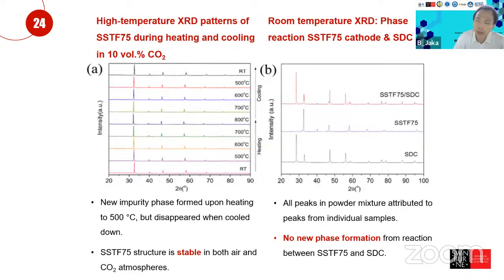And then we do a high temperature XRD pattern of the SSTF during heating and cooling at 10 volume % of the CO2, because this material is quite special. So we intend to use this in the single chamber solid oxide fuel cell. When I talk about the single chamber solid oxide fuel cell, you don't differentiate the chamber between the cathode